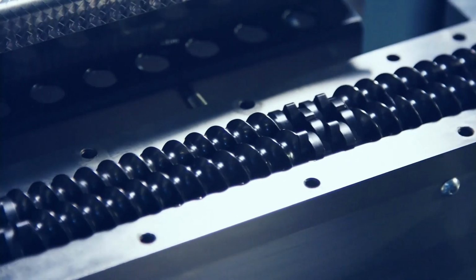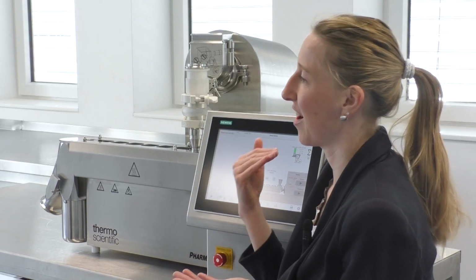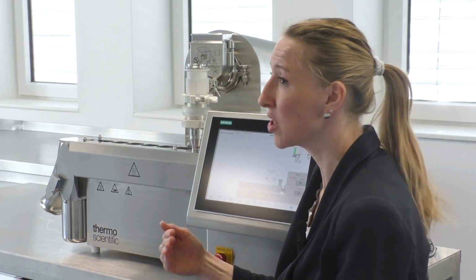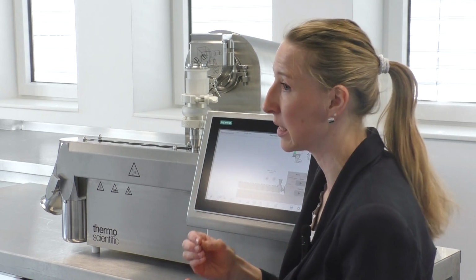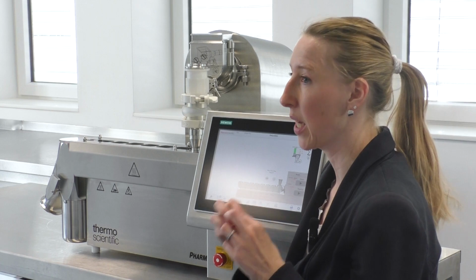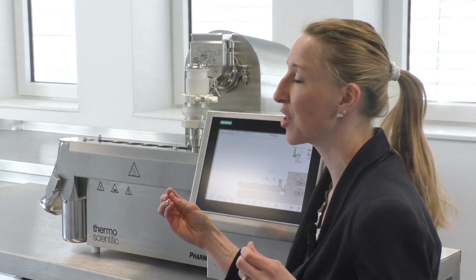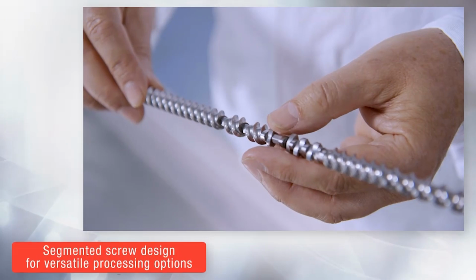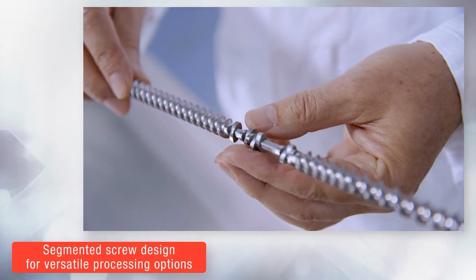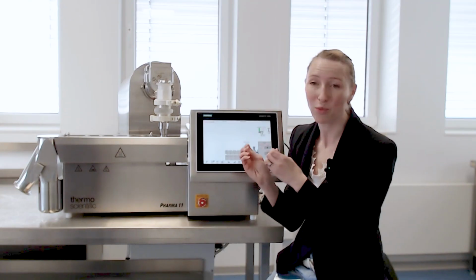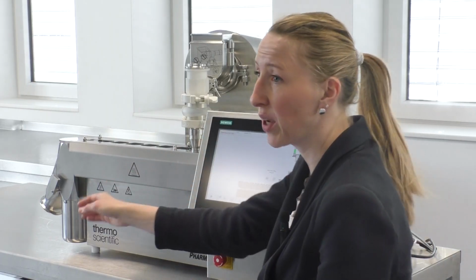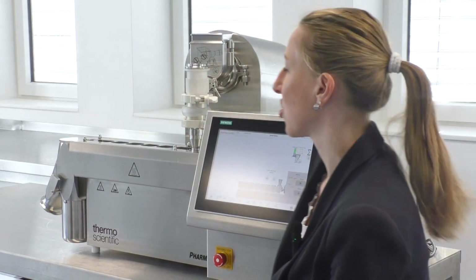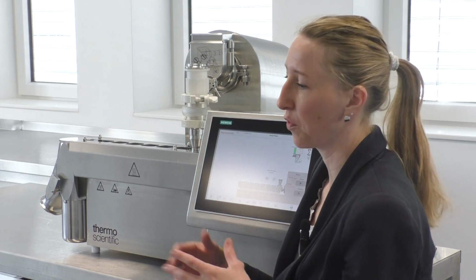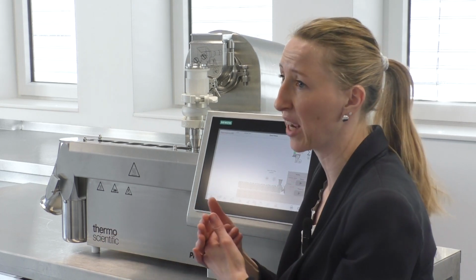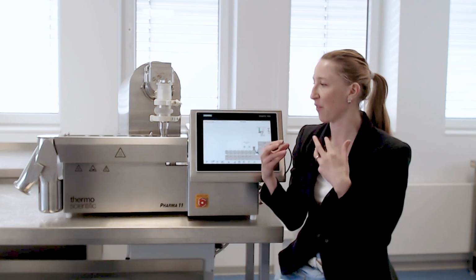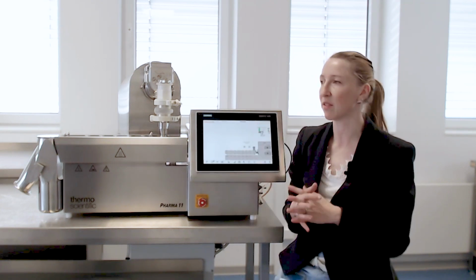So we can really reach high shear, a high mechanical energy that we introduce into the material if it is needed. The nice thing is we can really customize this screw configuration. And with this, we can basically process the material very customized to the needs we have in this process. The other point is we have an open discharge, and this allows for a free flow of the material, no compaction in the end. And with this, we can have really a continuous process. That's the biggest advantage, I guess.